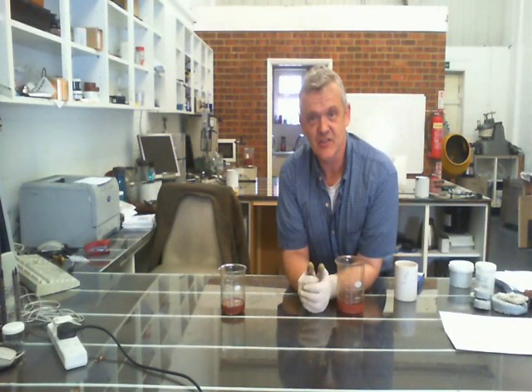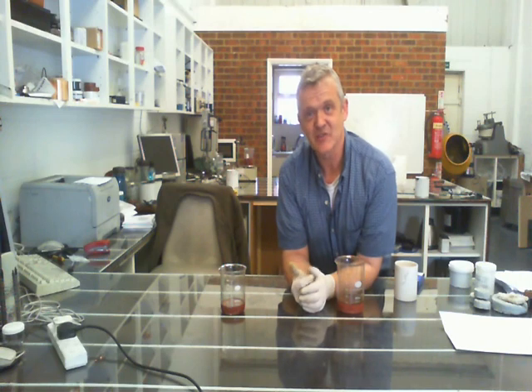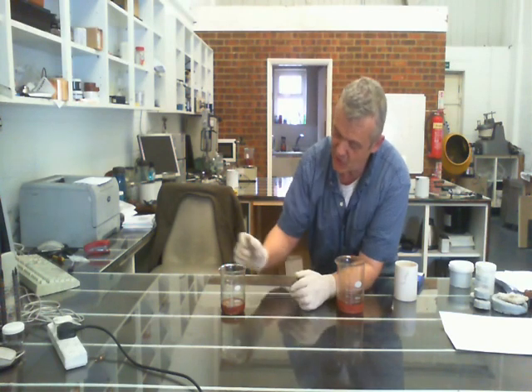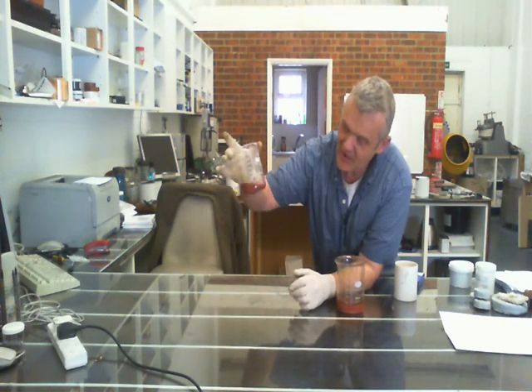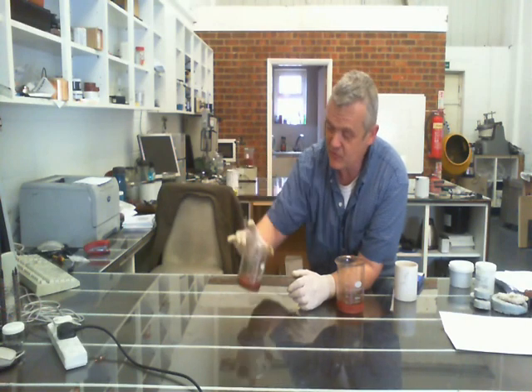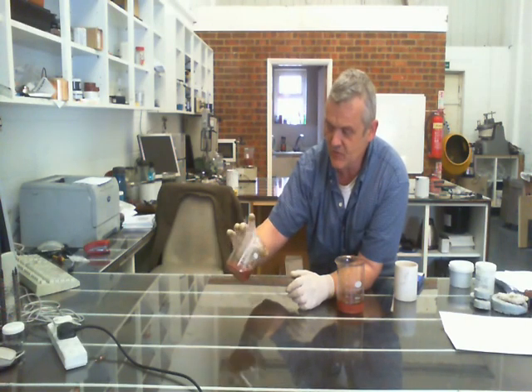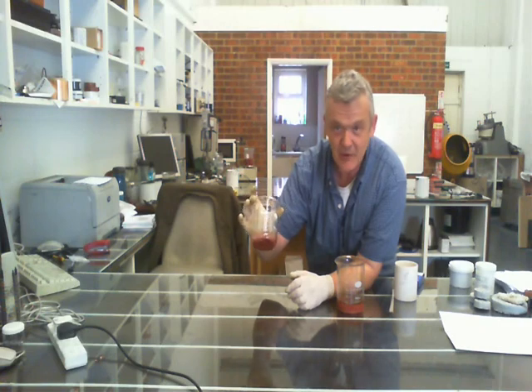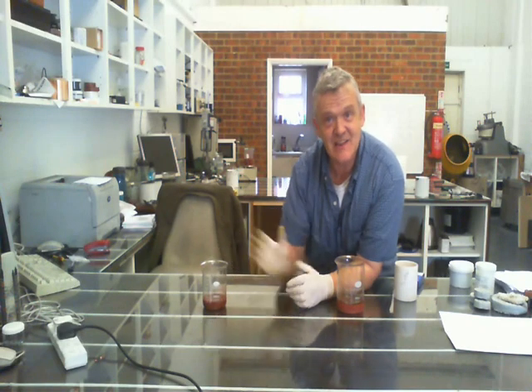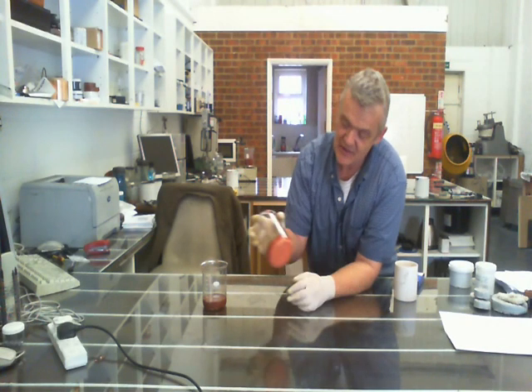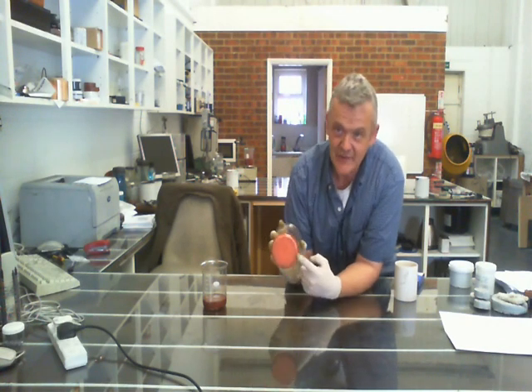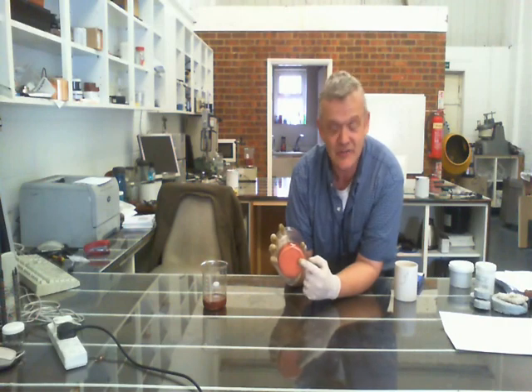Okay, so in the background you can see the gelatin and copper oxide and formic acid still stirring, and that's going to take about 6 hours or so. This has been in the microwave for about 12 minutes. And if you swirl it around, you'll see a layer of pink at the bottom. That pink is the telltale colour for copper nanoparticles. And you can see it in the set version there. It's a very bright pink. That's copper that's come out.